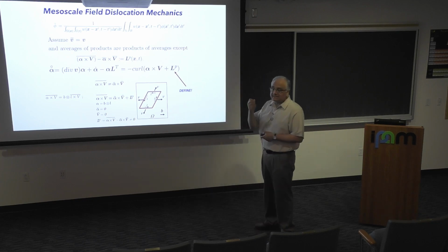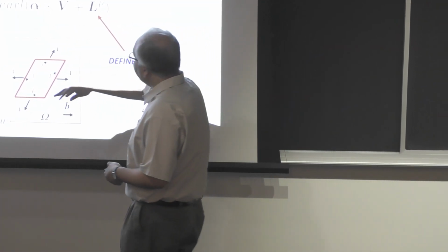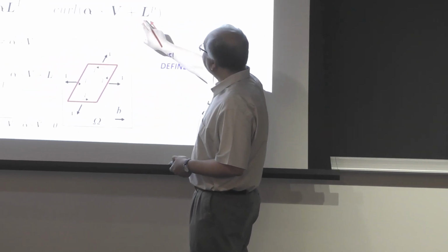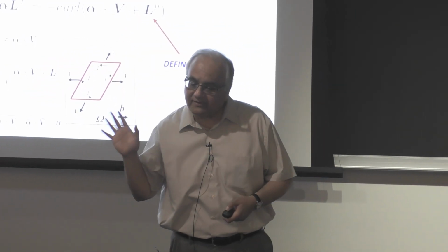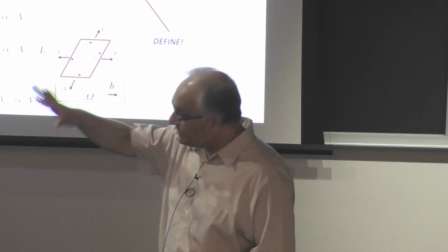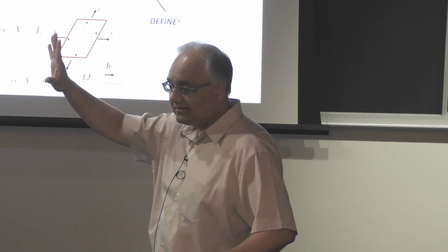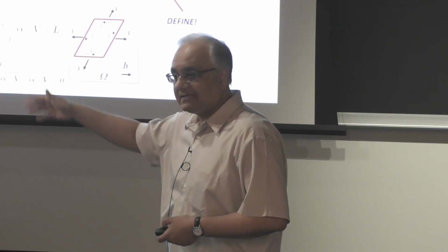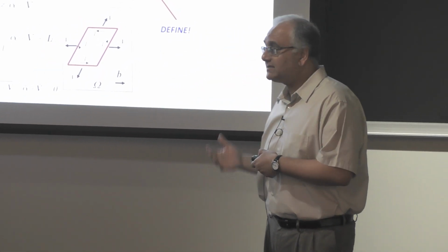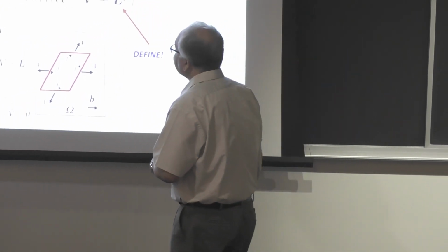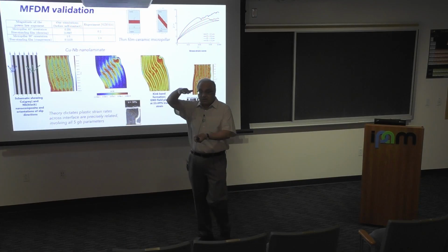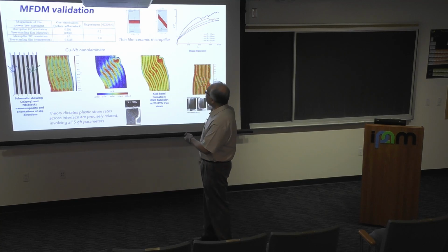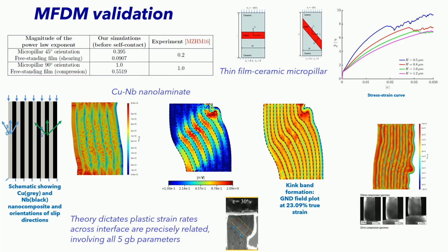So what I'll show you in a couple of slides is this. When you have something that you cannot fill in, we make the simplest possible assumptions on that, and don't get fancy on this. There is enough phenomenology developed about this, so we put that in, but there is still enough structure. For example, I talked about the nanolaminate business. For the micropillar compression, 45 degree, 90 degree, the experiment was 45 degrees, 0.2 was the exponent, 90 degree was 1.